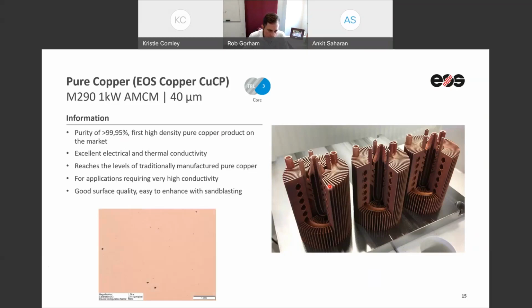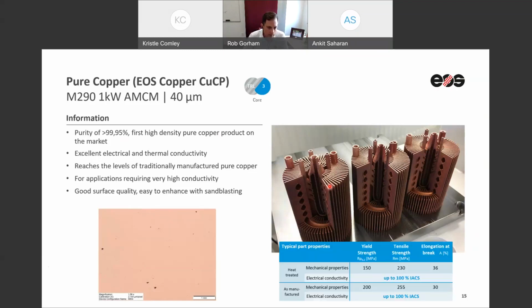And what you would expect from a material, you open it up, this is an example microstructure here, it's nearly completely dense. We're not talking about 94% dense or 93% dense. We are talking about almost 100% dense copper. So that's the part performance in terms of microstructure. And of course, when you do a heat treatment, you can expect a moderate heat treatment effect. And in terms of electrical conductivity, we've seen that you can almost achieve up to 100% IACS values, which is the prime criteria for down selecting some of these alloys.